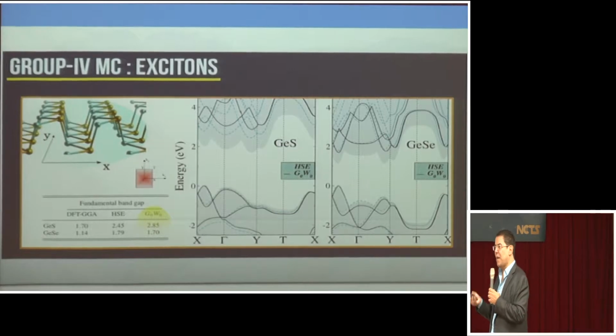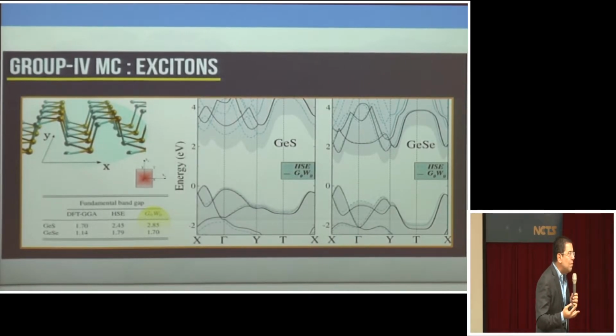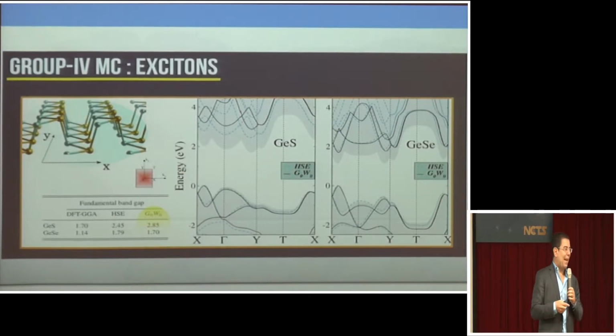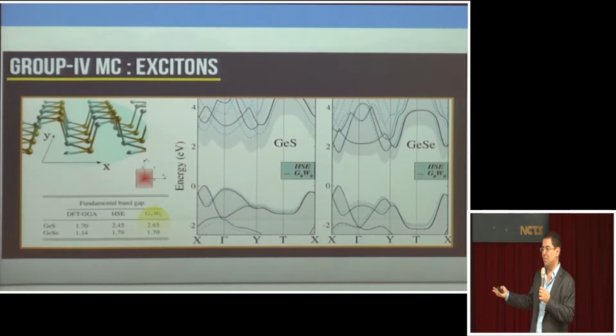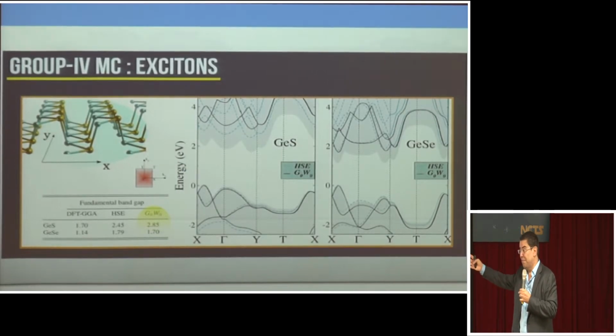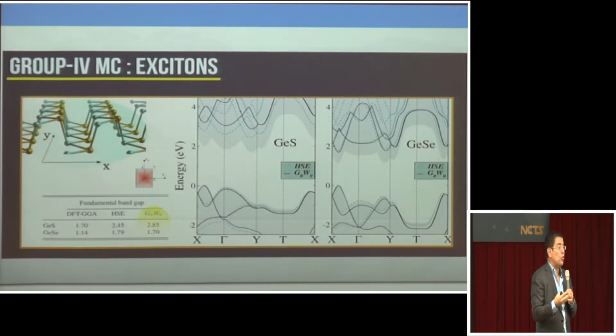This happens because in two-dimensional systems, electron-electron interactions are much stronger than in three-dimensional systems. Why is that? Electromagnetism happens in three-dimensional space. The electrons here are moving in two-dimensional space. Okay? So the electric field lines actually propagate away from the plane of motion of the electrons. If there is no dielectric medium outside of those layers, there is no screening. So essentially the electric field can propagate freely in the empty space, and that part of the electron-electron interaction is not screened. If you have a three-dimensional metal, the electric field has to propagate through the entire metal, and so the electrons in the 3D material will have a strong impact on how the interaction is screened.